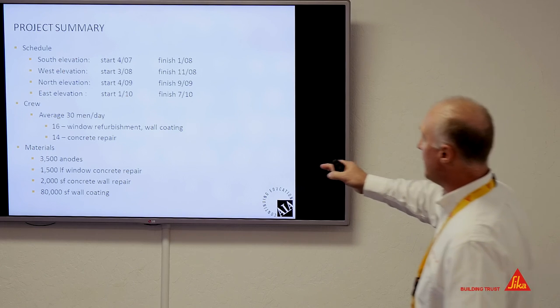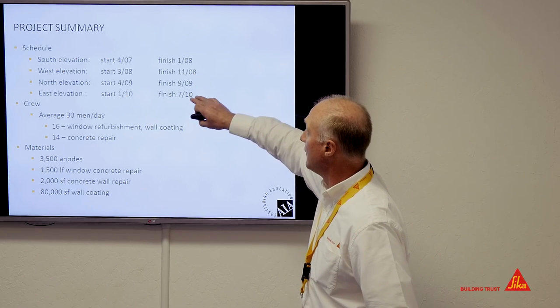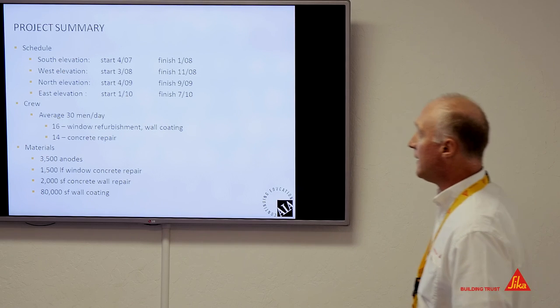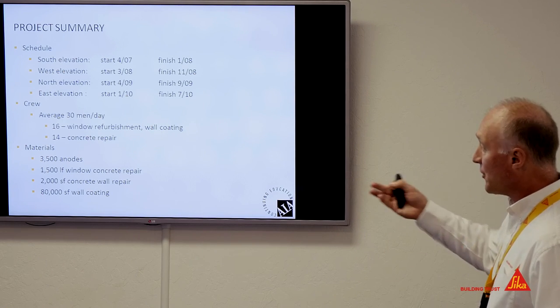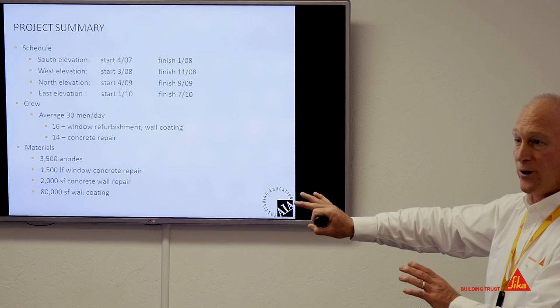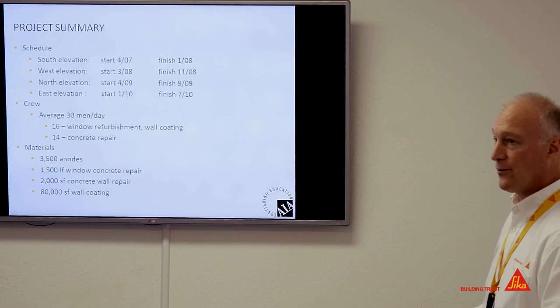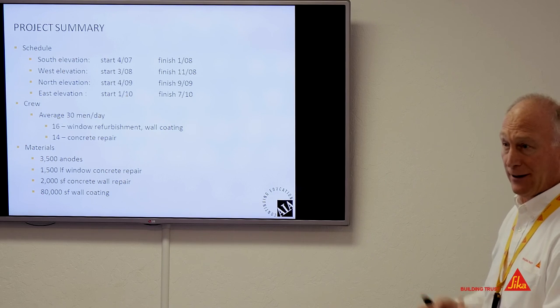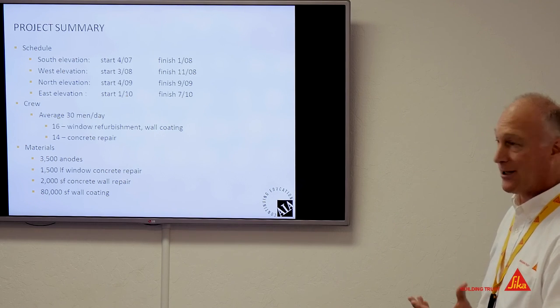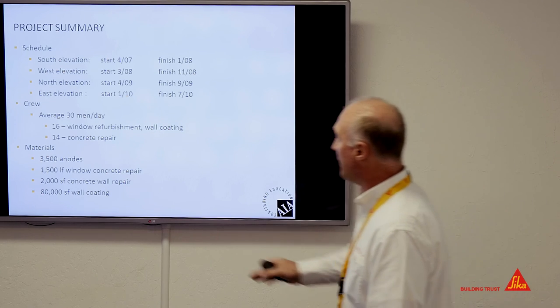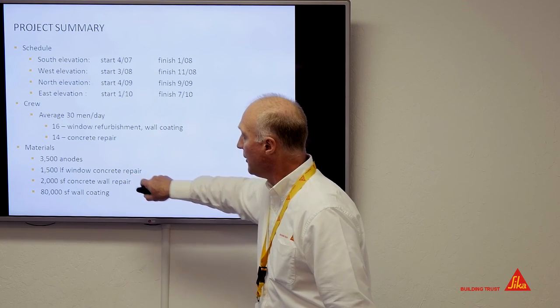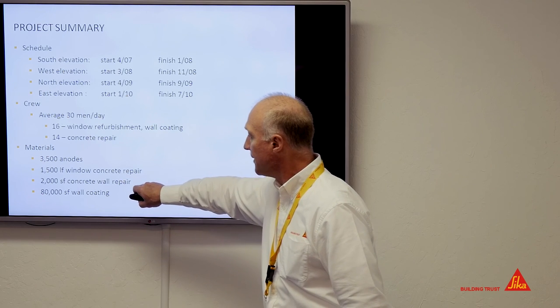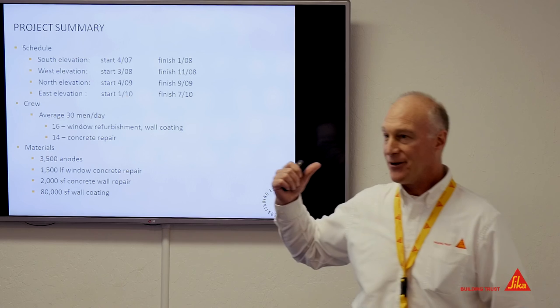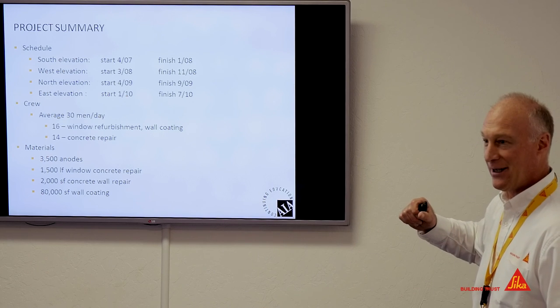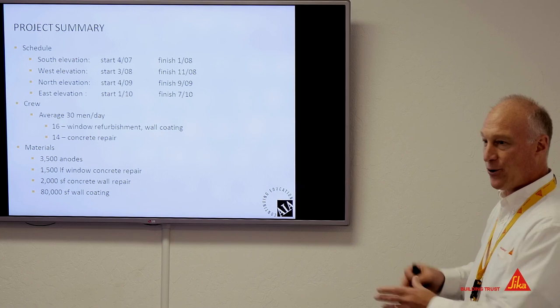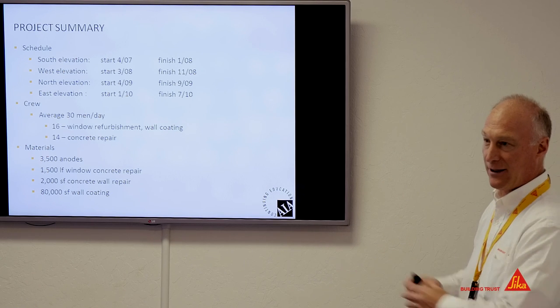So they approached each elevation year by year, starting in '08, finishing in 2010. They averaged about 30 men a day, almost split 50-50 between crews working on windows versus doing concrete repair. So it was a very large window repair and replacement project, as much as it was a concrete repair project. But some of the quantities, 3,500 anodes, 1,500 linear feet of concrete repair, 2,000 square feet. Keep in mind, on Sutter Street, it was 4,000 square feet. So it was a much smaller job, but twice the square footage of spalling.